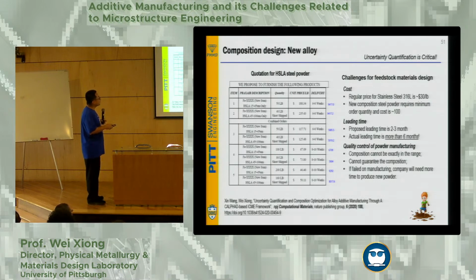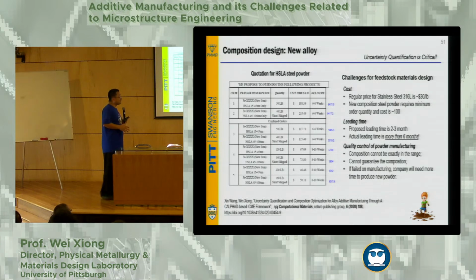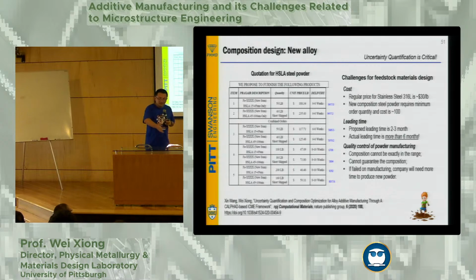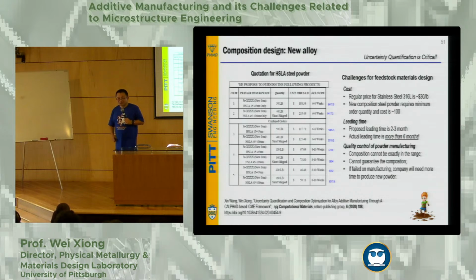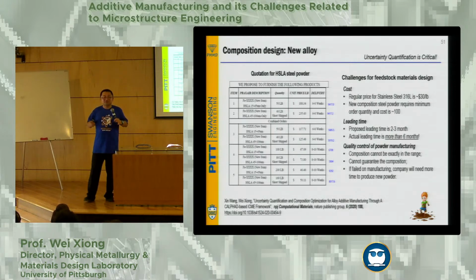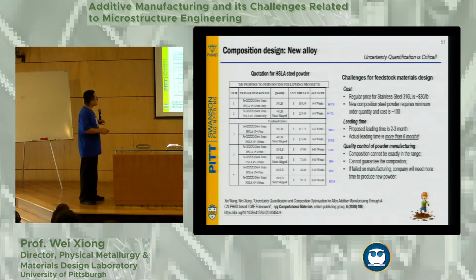And then qualification, right? How to control the composition of the powder. That's actually one section that I introduced yesterday. But it's very hard to control the composition. I checked with one of the vendors. They were saying, oh, the oxygen content we can reach is this amount. We cannot make it lower, okay? Either you accept or not. So no negotiation can be made with them. That's a limitation with a lot of powder vendors, right? So we have to bypass this challenge, right?